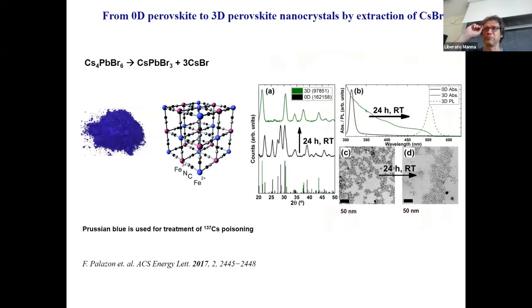So, for example, another typical reaction you can do on a perovskite is extraction of cesium bromide, actually starting from the cesium 4 lead bromide 6. Now, for example, if you get poisoned by cesium 137, which is strongly radioactive, doctors will give you pills of Prussian blue. This is a very small metal organic framework, and the size of the cage fits exactly the size of the cesium ions. So if you put, for example, the 0D cesium 4 lead bromide 6 nanocrystals in contact with Prussian blue, it will extract cesium and, of course, bromide ion as a counter anion.